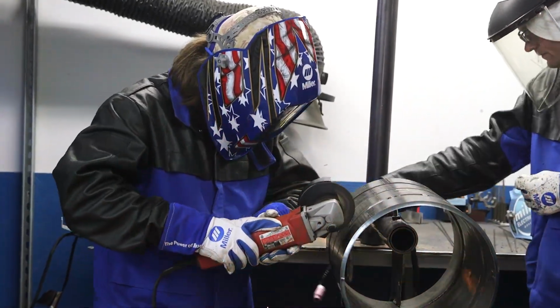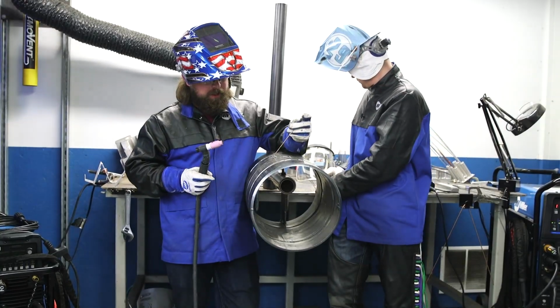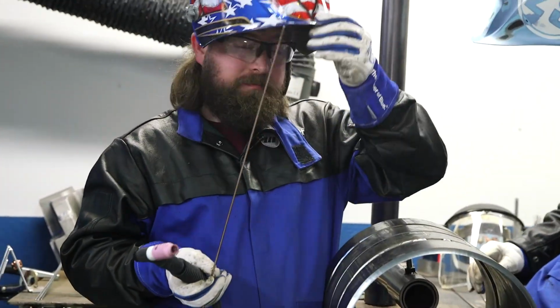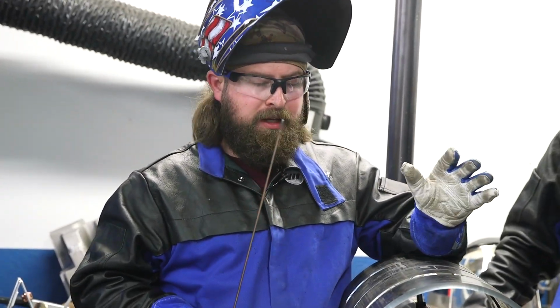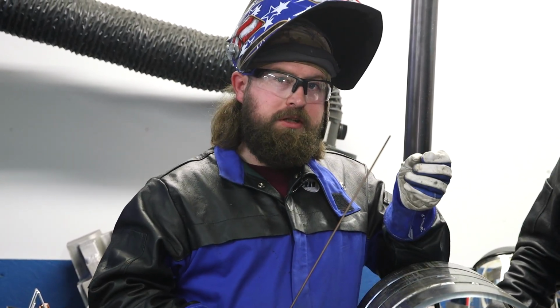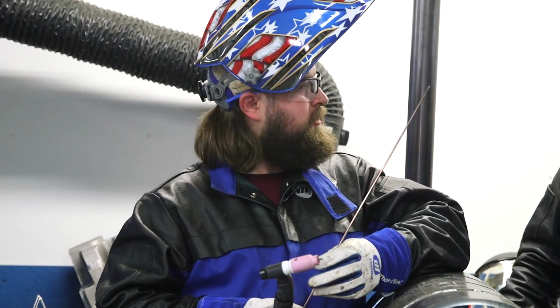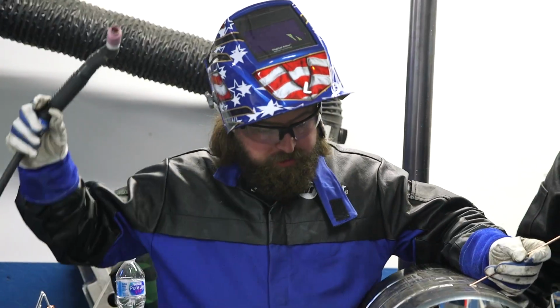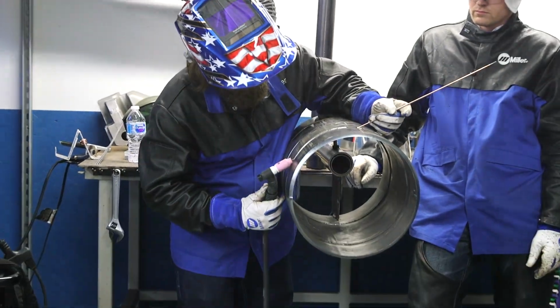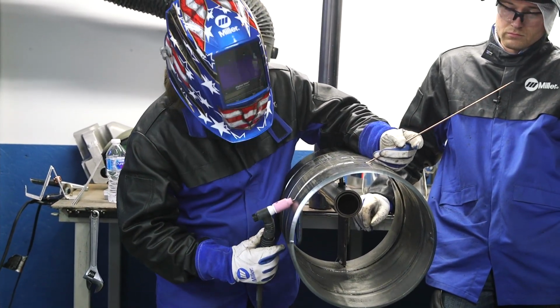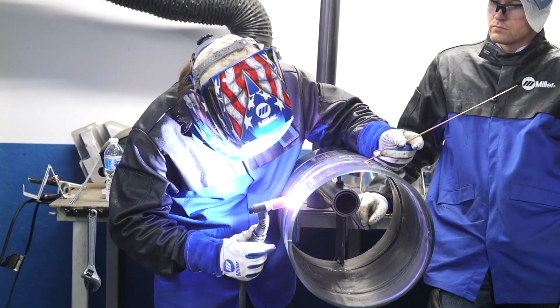Another thing to keep in mind with running a grinder through that gap is the potential for putting a burr, leaving an edge in there, and that might not always cause issues, but it has the potential. So using either a hacksaw blade or a banana knife or something along those lines, depending what your site allows, pulling those burrs out so they don't fuse to the edge of the puddle and leave essentially a nub sticking out, and then X-ray picks it up or visual. So it's just one other thing to keep in mind to ensure that perfection of a finished product.